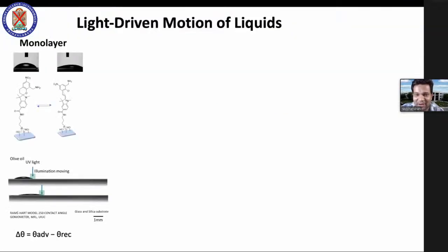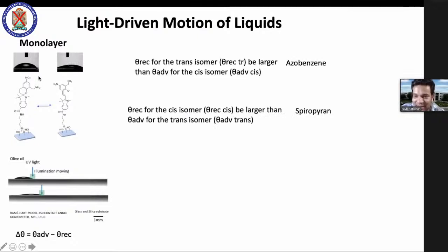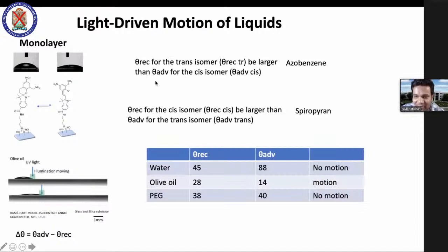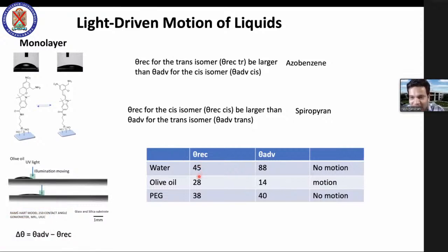So let me explain how it works. You have a biomolecular solution, and this is before excitation, and this is after excitation. We call these the advancing and the receding angle. So this is called the advancing angle, and this is called the receding angle. How do we check whether any droplet or biomolecules move on the surface? First, we need to measure the advancing and the receding angle. If the advancing angle is smaller than the receding angle, it means that it creates the motion.